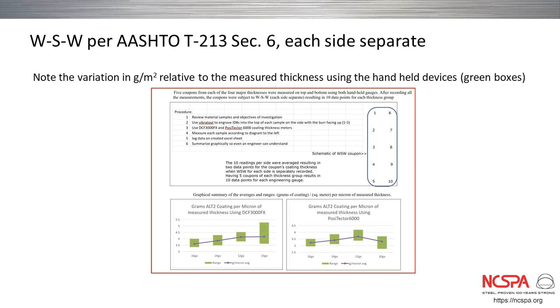On this comparison, we're doing weigh strip weigh data using the AASHTO T213 Section 6 Method A, which is the hot sodium hydroxide, rinse, cool, room temperature, concentrated hydrochloric, rinse and dry. We're using that as the umpire for coating weight via weigh strip weigh.